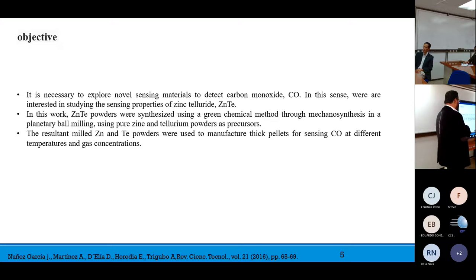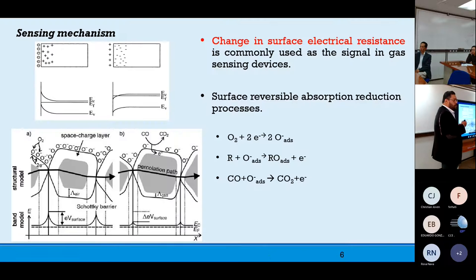In this work, zinc telluride powders were synthesized using a green chemical method through mechanosynthesis in the planetary ball milling, using pure zinc and tellurium powders as precursors. The resultant zinc telluride powders were used to manufacture pellets for sensing CO at different temperatures and gas concentrations. But how does a sensing material work for this application? Well, the sensing mechanism is the following. It's in this slide.